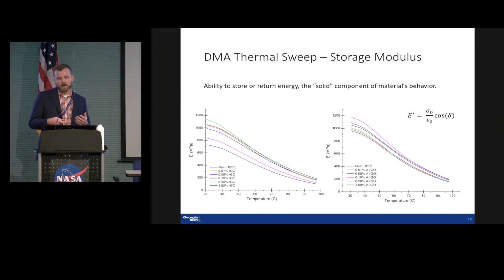So a little more quantitative, we've done some DMA thermal sweeps so far, and I'm just going to show you the tan delta and the storage modulus, which is what I have here. On the left, we have reduced graphene oxide, and on the right are the composites featuring the alkylated reduced graphene oxide. And as we see here, in general, the performance of the reduced graphene oxide is less than that of the alkylated reduced graphene oxide, which makes sense. That's what we would expect from this better mixing.